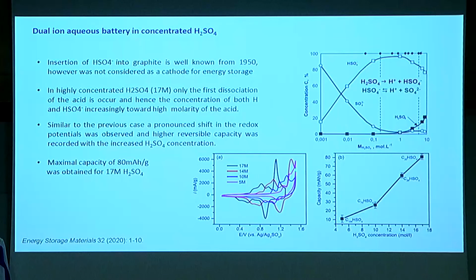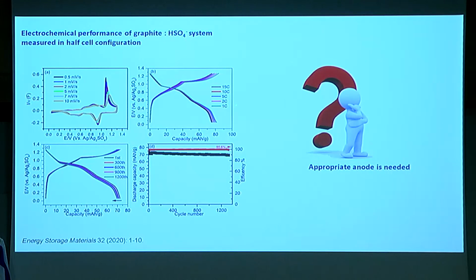So here you can see that indeed in 5 molar you cannot get any significant reversible capacity, while changing to 17 molar we can get perfect intercalation of bisulfate into graphite. And just to mention here, graphite is not an anode, it's a cathode, because it works with anions. And you can see here also that the capacity in this 17 molar was 80 milliampere hour per gram, and here we have a ratio of 1 bisulfate per 20 carbon atoms. Okay, so the performance of the half cell of graphite: you can see that it works, it has very fast rate capability. There is no dramatic difference between a 1 C rate and a 15 C rate.